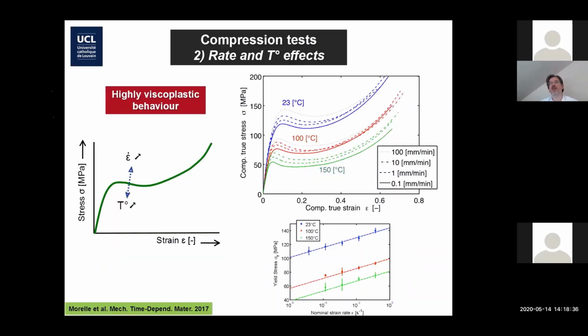But on the other end, the viscoplastic behavior is significant in terms of the rate sensitivity. So on the right side, you see blue, red, and green curves, 3 different temperatures, so big effect of temperature, of course, and big effect of strain rate. The curves are given for 4 different strain rates, displacement rates here, where you see a big effect. This is below the evolution of yield stress with strain rate.